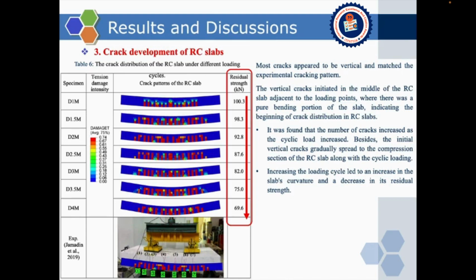It could be observed from the results that most cracks appear to be vertical and match the experimental cracking pattern. The vertical cracks initiate in the middle of the RC slabs adjacent to the loading points, where there was a pure bending portion of the RC slab, indicating the beginning of crack distribution in RC slabs. It was found that the number of cracks increased as the cyclic loading increased. Besides, the initial vertical cracks gradually spread to the compression section of RC slabs along with the cyclic loading.